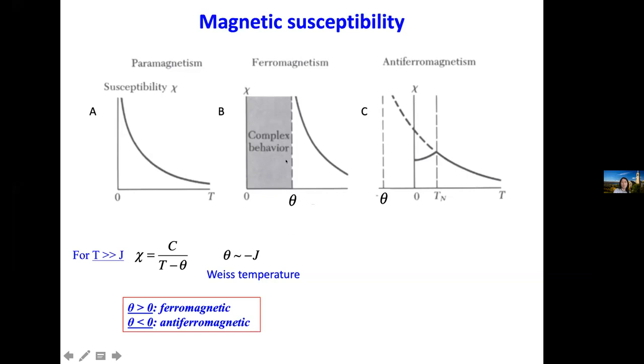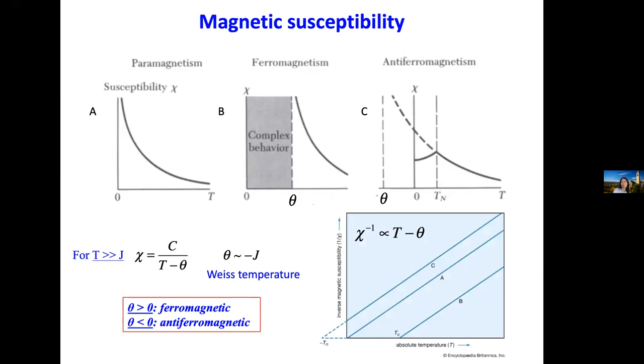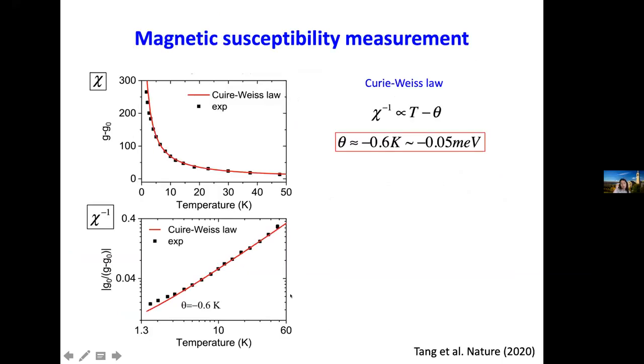If the susceptibility diverges at 0, that's paramagnetic. If it diverges at a positive temperature, that's ferromagnetism. And if it's at a negative Weiss temperature, it's antiferromagnetism. Experimentally, it's more convenient to plot 1 over chi and do a linear fit. And this is the result.